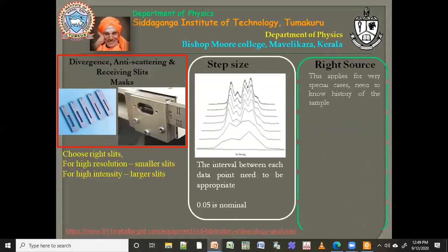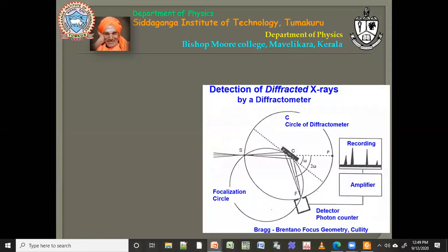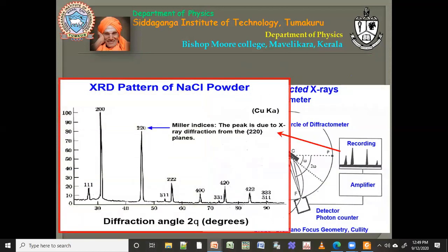Sir, there is a question from Prima C. Thomas: how is X-ray diffraction useful in polymer samples? If you are using a polymer sample, you can go for quantifying the crystallinity. And if you are doping something in your polymer, for example zinc oxide or iron oxide or some other oxide, then you can know whether your doped inorganic material is present in your polymer or not.